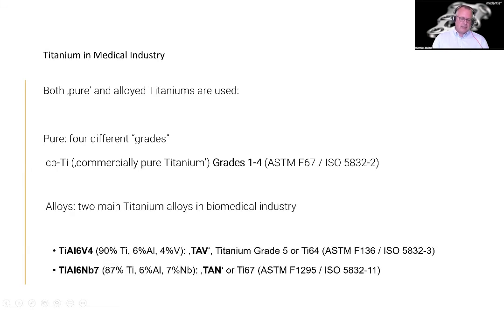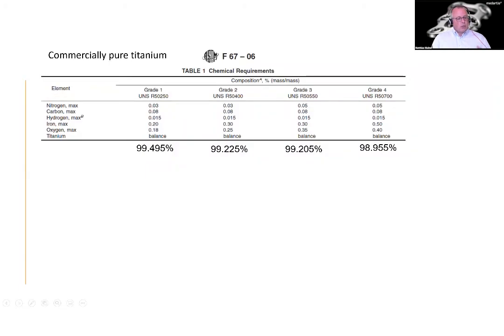And as I mentioned before, we have those titanium alloys like titanium aluminium vanadium, titanium niobium, for instance, when it comes to screw manufacturing, because you want the screw to be as thin as you can possibly go, right? That's why you want a material that has a very high tensile strength. Now, commercially pure titanium is called commercially pure titanium because it comprises nearly 100% titanium. Having said that, from grade 1 to grade 4, there is a tiny difference, a tiny balance when it comes to